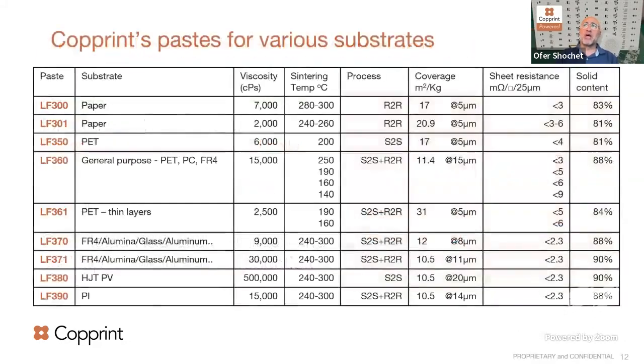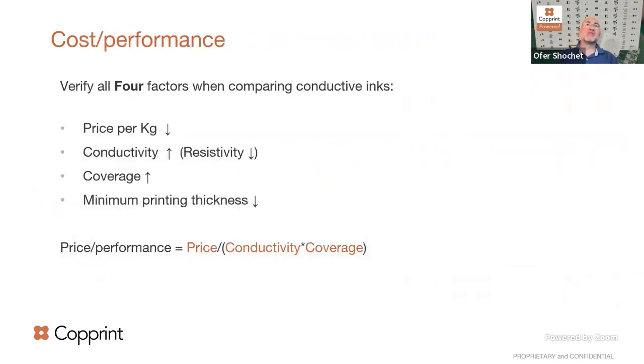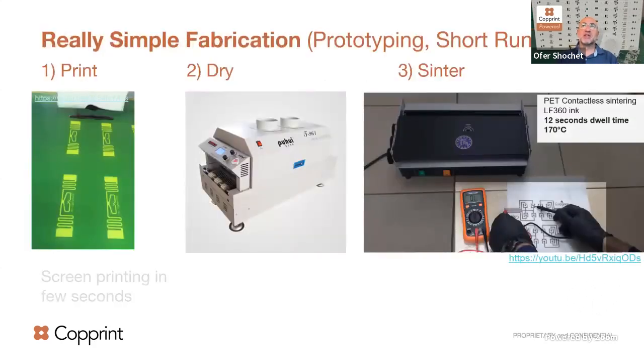So we are in serial production now. We have a lot of inks. There are details that I will not go into in such a short presentation. I will just mention that there are 4 parameters when you compare different inks: the price of the ink, the conductivity, the coverage, and the minimum printing thickness. And all of this will determine your price performance. And as I mentioned, with copper, usually we are getting 5 to 10 times better price performance than silver.